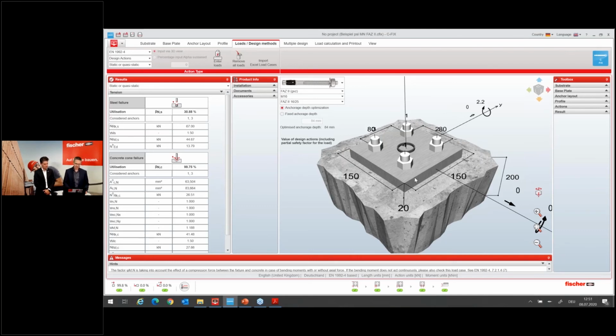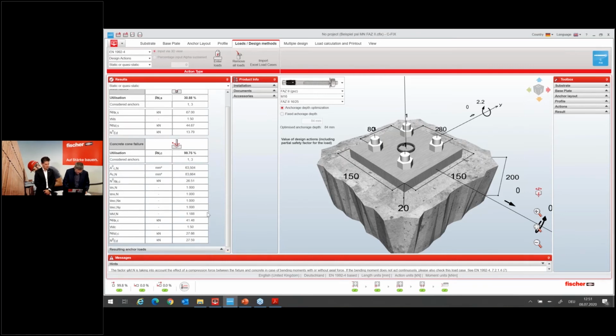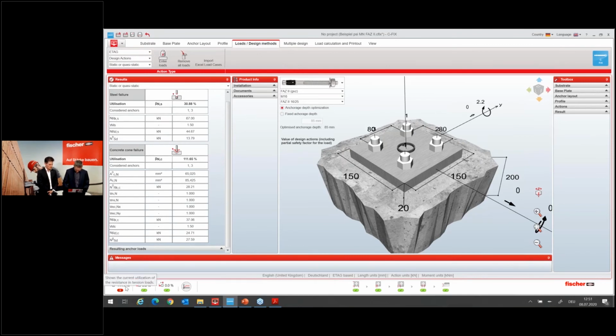Design is now according to EN 1992-4. If you look at the utilization degree, it is below 100%. And if you look in the results, now it's getting pretty small. The factor CMN is 1.19 in this case, which is due to the fact that you have a compression force under the fixture and that your inner lever arm is relatively small. If you change now to ETAG design, then you'll see that the utilization degree increases to 112%. So it is overloaded, and by designing with ETAC, you would need to change either your anchor configuration or your anchor type to get the load transferred.